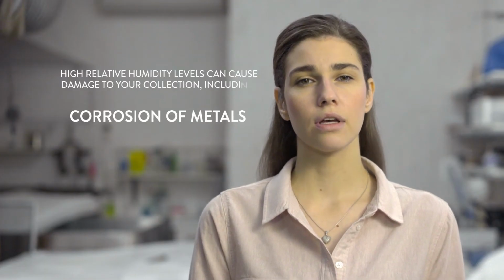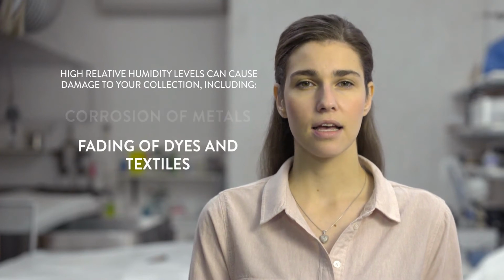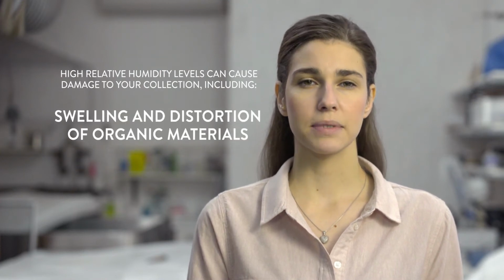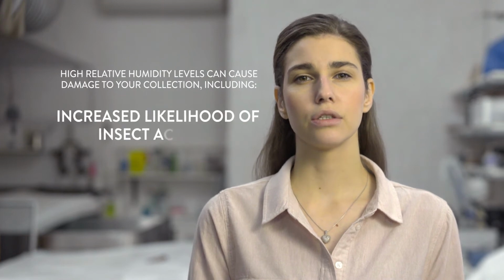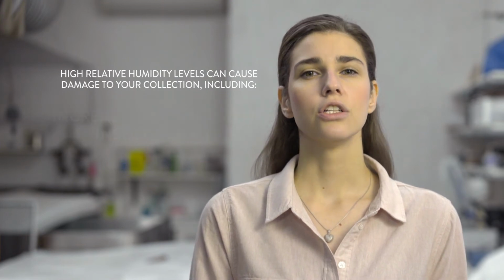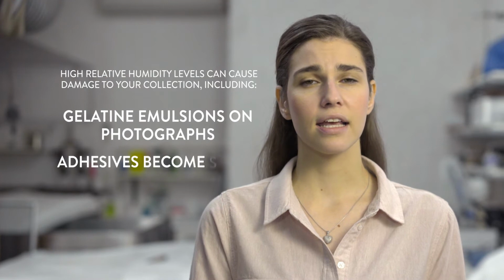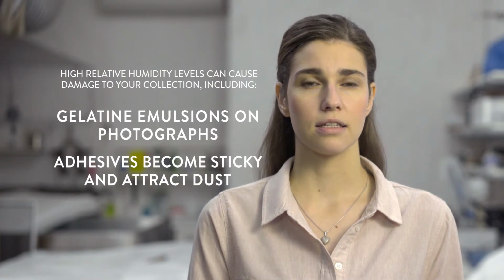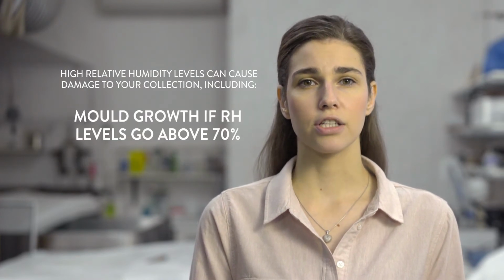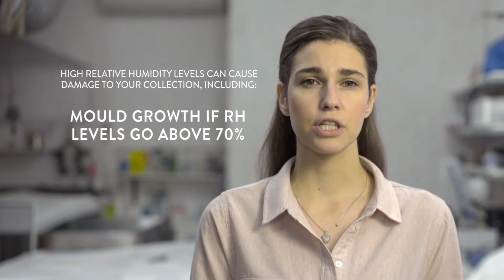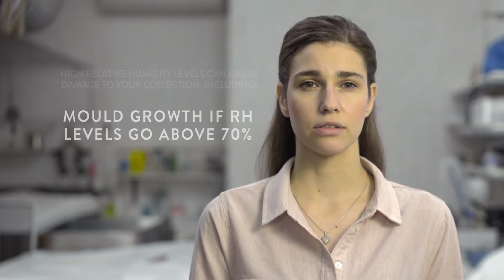Very high relative humidity levels can cause damage to your collection in several ways, including corrosion of metals, fading of dyes and textiles, swelling and distortion of organic materials, and increased likelihood of insect activity. Gelatin emulsions of photographs and adhesives become sticky and attract dust. Mold growth can occur if RH levels go above 70%, especially when there is poor air circulation.